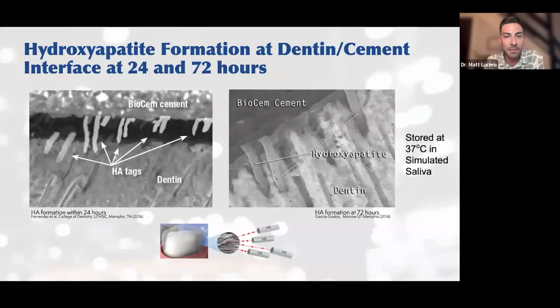Here's some SEM images of BioCem after 24 and 72 hours. So the bioactivity is really just hydroxyapatite forming within the tubules. And if you don't do those little waiting steps that I described to you, you're not giving the time for those little tags to start developing within the dentinal tubules. And because you waited a little bit, once you've done that light cure, there's already some within the tubules that are a little bit out of reach of your light. So they're going to continue penetrating over time. And at 72 hours, your bond strength is only going to continue to increase.